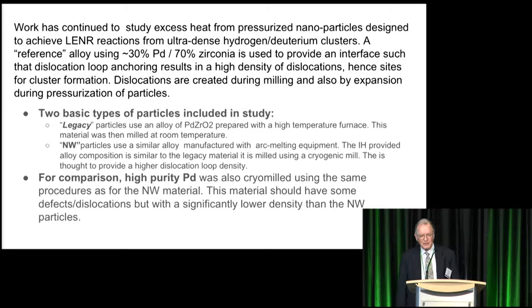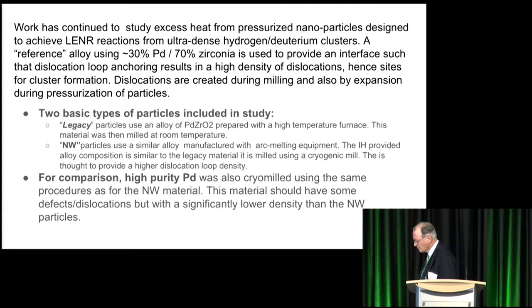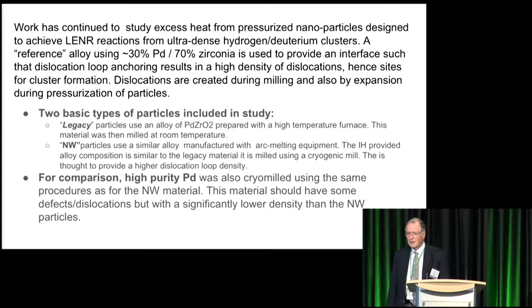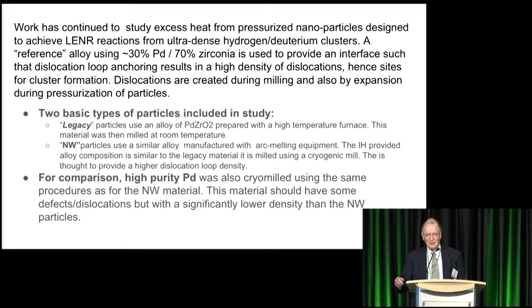Much of the approach goes back to the manufacture of the nanoparticles. The trick is to figure out how to prepare them so they have increased defects, enabling a high density of clusters within the nanoparticles. We have studied two different types of nanoparticles of the same composition — roughly palladium and zirconia. The zirconia is a separate phase that condenses out into palladium during manufacture such that it can anchor the formation of defects, which in turn are where the clusters form.